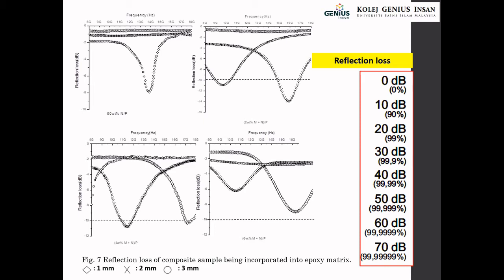For all of these samples, the highest reflection loss was achieved when the multi-wall carbon nanotube content was 2%, and the reflection loss of multi-wall carbon nanotube nickel zinc ferrite with a thickness of 2 mm was below -10 dB, which represents 90% of the electromagnetic wave being absorbed, within the range of 14.5 GHz until 17 GHz.